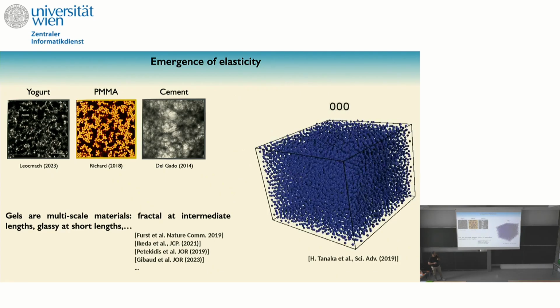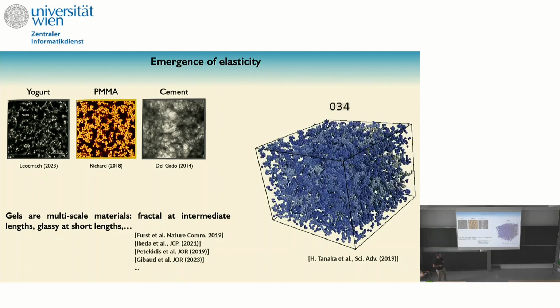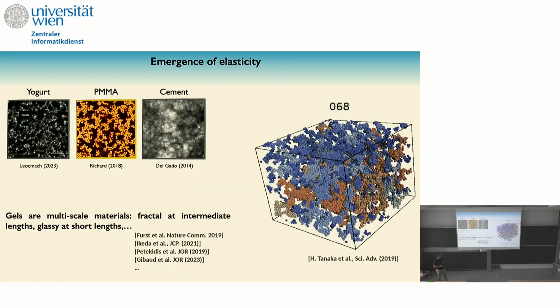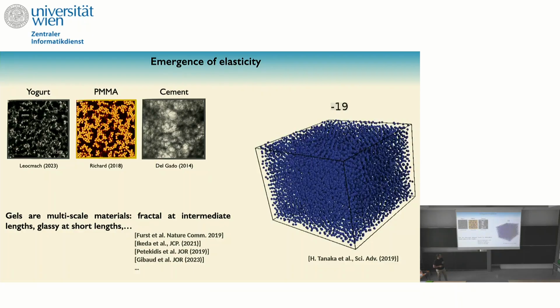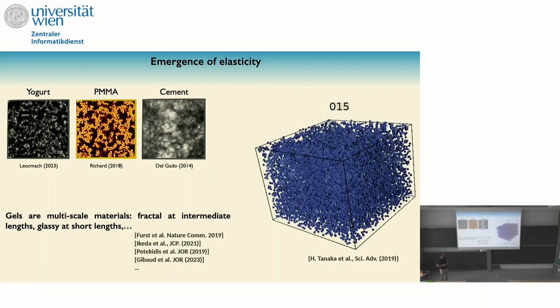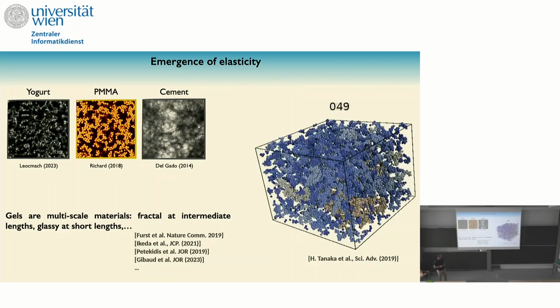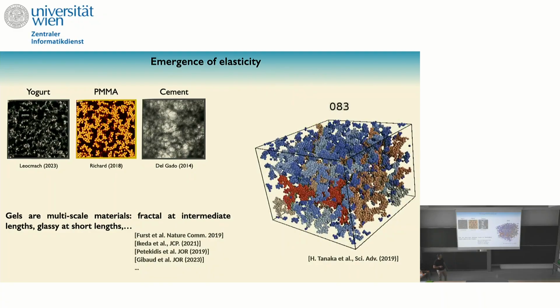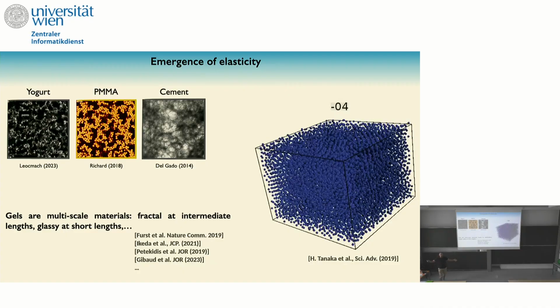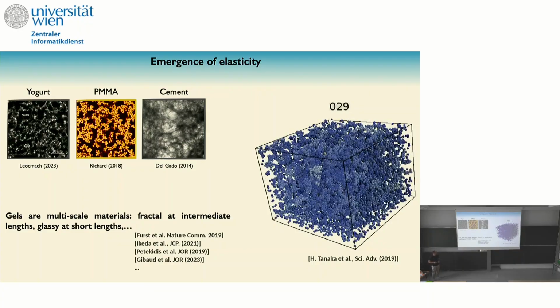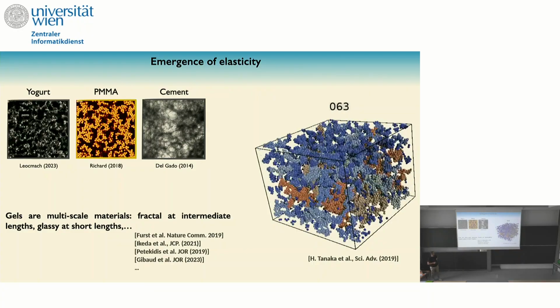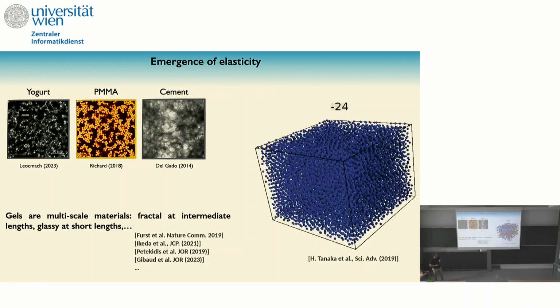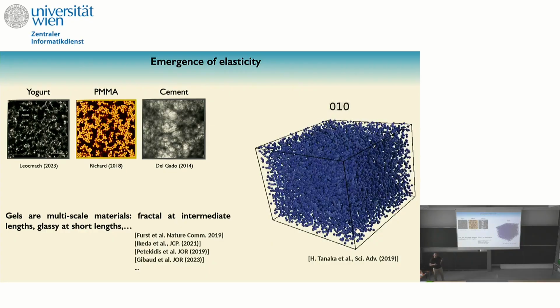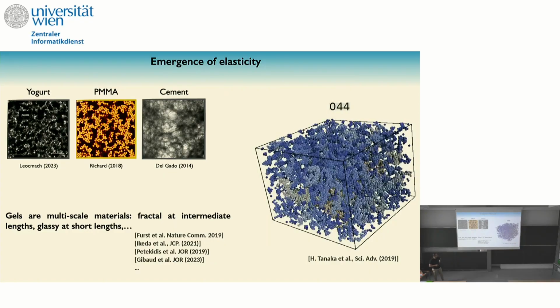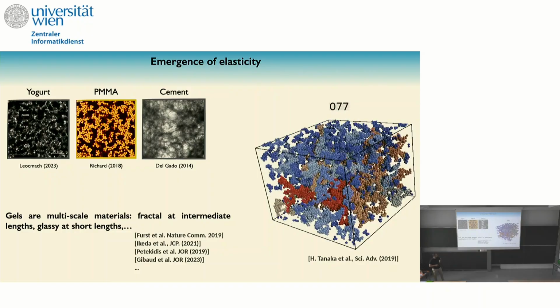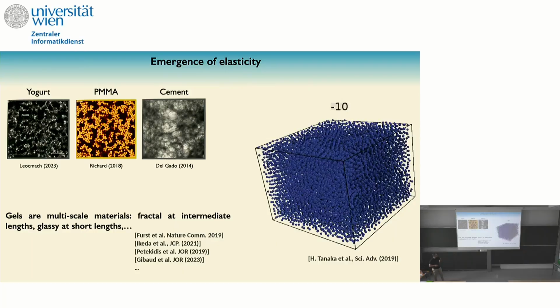Here I'm showing a video of an experiment in the Tanaka group, where they follow the gelation process and how the elasticity emerges. The color that you see is related to the clusters that they form. You see the system start as a fluid, and then the particles start to aggregate together and form some clusters, and then at some point the clusters merge together to percolate over the whole system. These systems are complex in the sense that they are multi-scale materials. You have different characteristic length scales from a structural point of view. They can be fractal at intermediate length scales, they can have some glassy phase at short length scales, and so on and so forth.